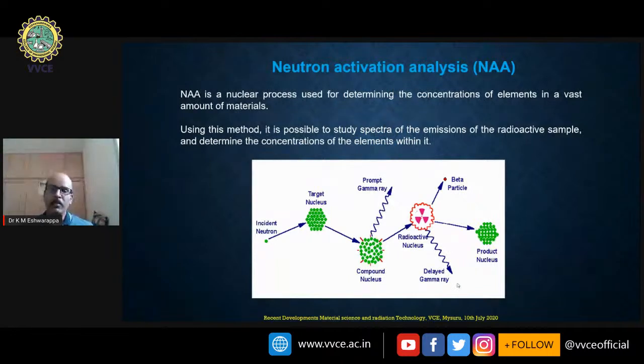Generally, people use the delayed gamma ray because doing prompt gamma ray neutron activation requires a lot of advanced techniques, where there is a background of neutrons as well. In the case of delayed gamma ray neutron activation, you can take the sample out of the radiation environment, into a neutron radiation free room, and there the post irradiation analysis can be made. In that case, of course, the sensitivity is less for delayed gamma rays compared to prompt gamma rays. But still, we can estimate up to nanograms using the delayed gamma rays. Whereas in the case of prompt gamma rays, we can estimate even the presence of an element up to picograms.